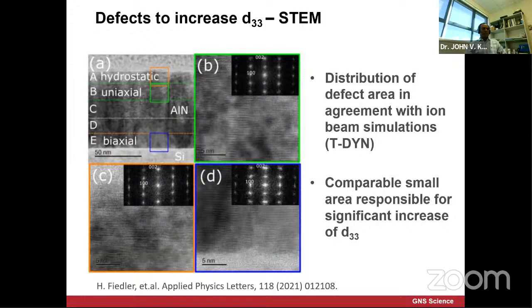And also if you compare with the Monte Carlo simulations we did earlier, which correspond to regions A and B. If you remember the selection of regions in my simulation diagram in the third, fourth slide, we selected a few regions where aluminum meets nitrogen rate. So that corresponds to here. We can compare this with the significant increase in the changes of D33, which is amazing. We are able to directly, theoretically calculate the defects and experimentally locate where the defects are going and how they are changing it. You can imagine the scale bar. It's a really high resolution STEM image. You're talking about nanometer or less resolution. So that gives you a very good idea of how the lattices can change, because the defects we are talking about are very minor.